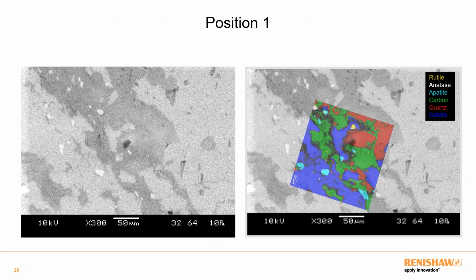So now I want to go through the results of the individual positions. This is position 1, and first of all I'll try and talk through the SEM image. This is a backscattered SEM image. Broadly, it gives information on the atomic number of the elements in the sample. Where the image is brighter, the element is heavier. So we can see there's differing compositions here. It's not dependent on topography.